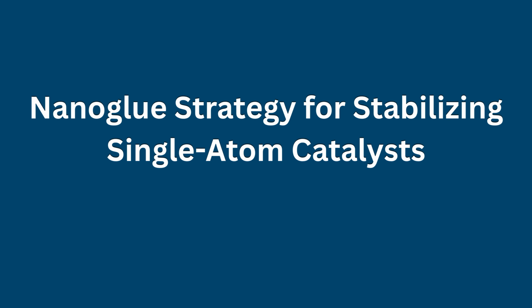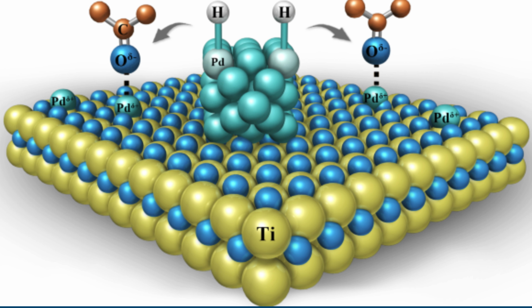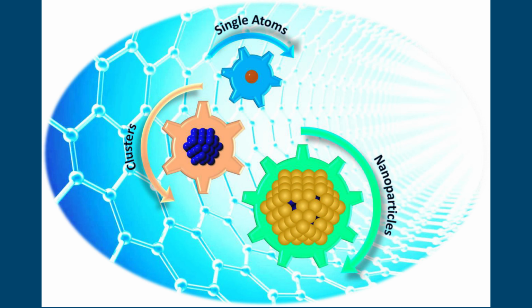Nanoglue strategy for stabilizing single-atom catalysts. To address the stability-activity trade-off, a three-component catalyst design has emerged: a high surface area support, for example, silica or alumina; dispersed oxide nanoclusters, the nanoglue; and atomically dispersed metal species, M, localized on these clusters. In this architecture, oxide nanoclusters act as anchoring domains that strongly bind metal atoms while preserving their mobility within confined regions, enabling catalytic turnover without aggregation.